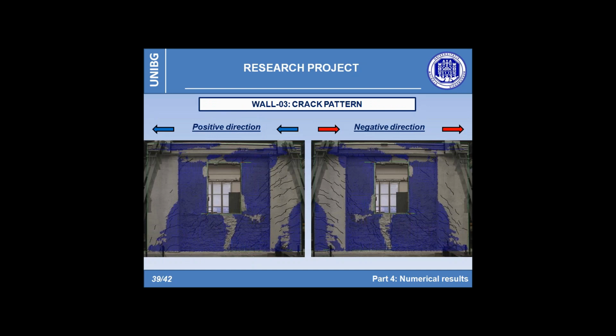The result of a superimposition between numerical prediction and experimental cracks, in the hypothesis of a monotonic action, confirms the potentiality of the proposed model to describe the main mechanism, highlighting at the same time the drawbacks previously mentioned. Also in this case, in fact, the shear walls are affected by a more extensive damage with respect to what is predicted by the finite element analysis. With respect to wall 2, the shear walls seem to be affected by cracks along their entire height, confirming that the presence of the inferior spandrel slightly affects the crack pattern of the structural walls due to high shear stress, as in a short column effect.